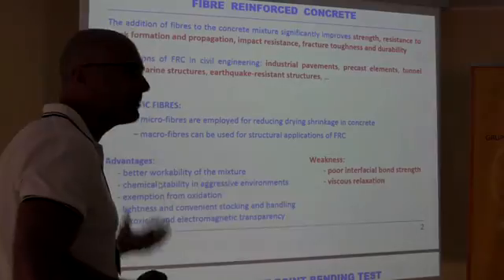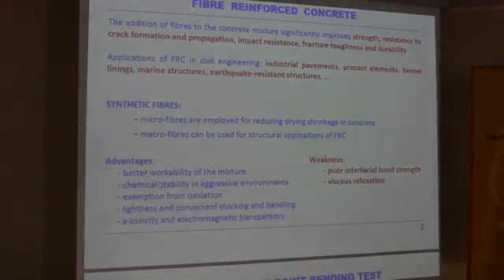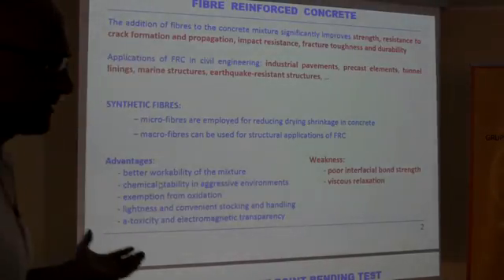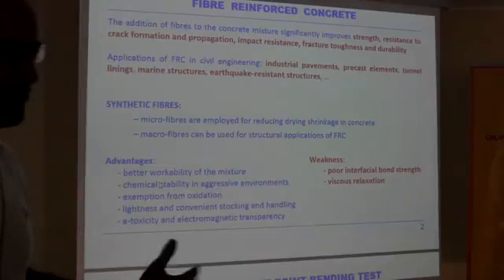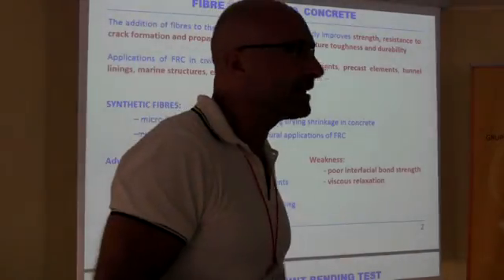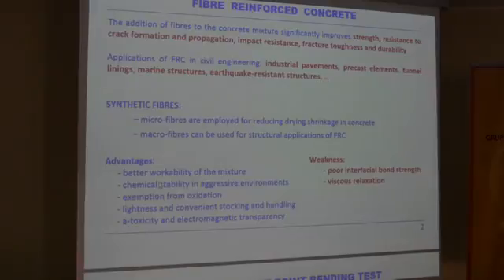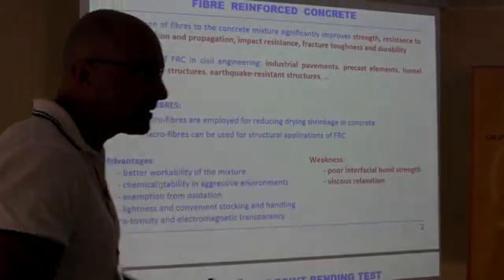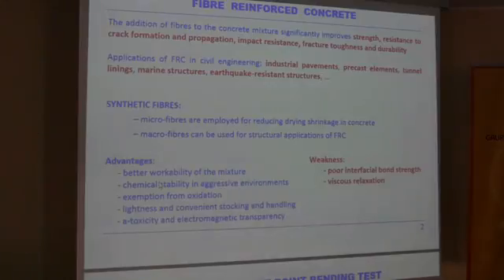with the electromagnetic waves. However, the main weakness of these synthetic fibers is the poor interfacial bond strength, since polymeric and concrete are two different materials. One is hydrophobic and the other is hydrophilic. So the bond characteristic is quite low. Moreover, they have some viscous relaxation behavior, which should be taken into account, but this will be done in a second step.